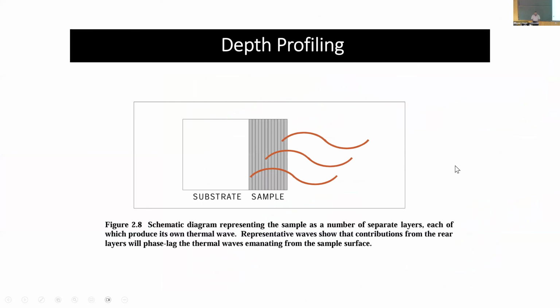Okay, one last aspect before I switch to the other basics. This system actually measures heat, right? I told you it measures non-radiative relaxation. Heat basically diffuses out of a material at a constant rate. No matter what light you shine, you produce some heat, and that heat diffuses out at a specific pace, and that parameter is called the thermal diffusion coefficient. In every material that's a constant, it doesn't change, it's very permanent. Absorption is not, heat is.